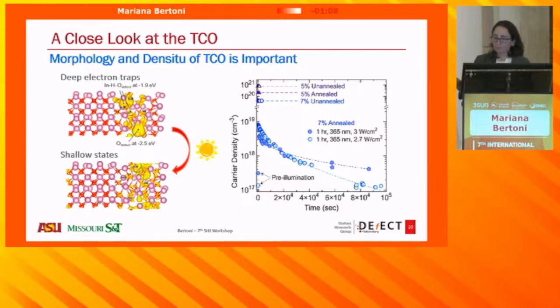And one final thing is that many of you have probably seen some weird things happening in the TCO. Yes, weird things happen in the TCO. When you start actually shining UV light in the TCO on top of your amorphous silicon stack and you see that hydrogen basically out diffusing, you start seeing a lot of changes in your carrier density and a lot of changes in your mobility. And that usually originates from creating some deep electron traps and some shallow states. And I'm happy to chat about those if you are interested.